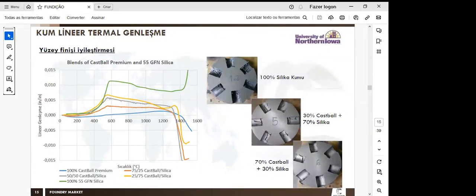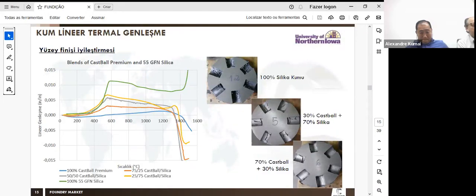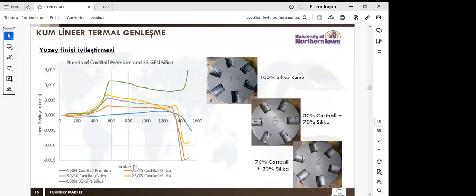Here we have another example. When Castball is added to a silica sand mix, the total thermal expansion of the mix is reduced. The thermal expansion results obtained for silica sand with Castball show it. Additionally, the surface finish of the casting tryouts has proved it. The amount of veining is reduced as the amount of Castball in the silica sand mix is increased.